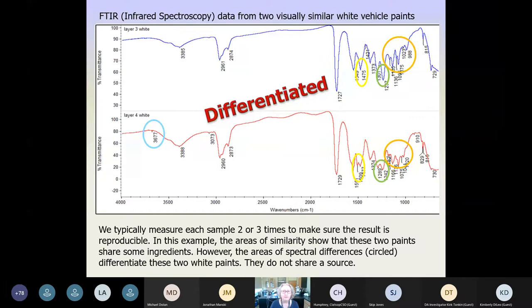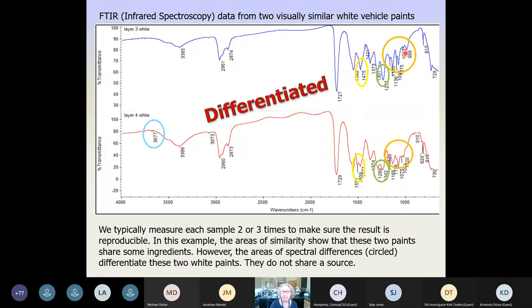Here's an example of what FTIR infrared data looks like. We have two white samples that are somewhat similar — they both have a large peak around a certain region and some areas in common, which tells us they could share some ingredients. However, the circled areas show that when comparing the fine detail of where the peaks are from one sample to the other, they are discriminated — they are different. Even though some ingredients may be in common, the mix of ingredients in the top white paint is different than in the bottom white paint, so those two white paints do not share a common source.